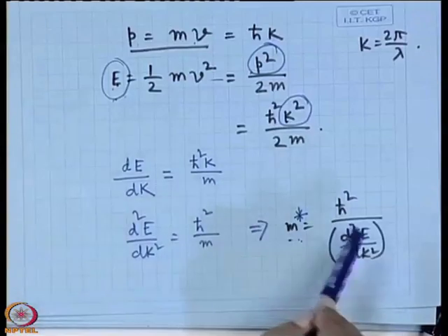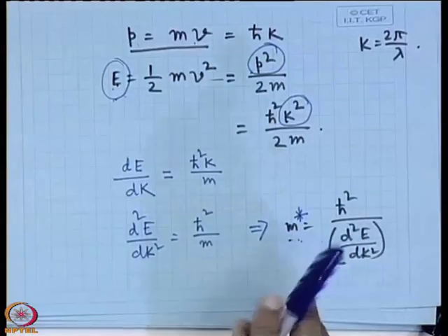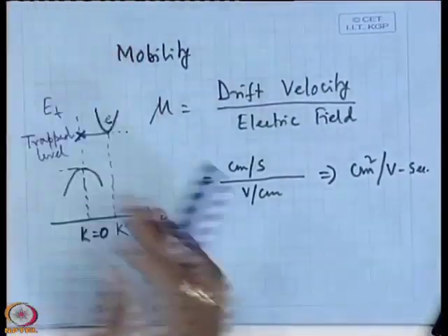Okay. So, one point is that the band structure will determine the mobility, and another thing is that the band structure will give rise to either direct or indirect type of recombination. That means the recombination can be radiative or non-radiative type. So, the material can be used as optoelectronic sources or cannot be. Okay. So, up to that point, if you have any question, please feel free to ask me.